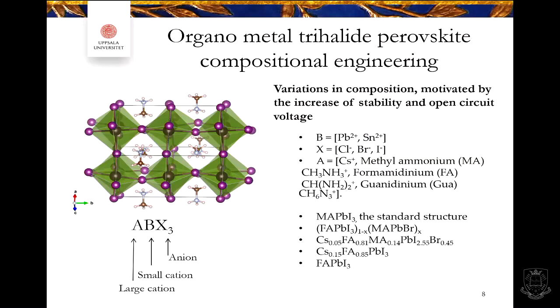So one other property which is unusual for semiconductors is that you can vary the band gap so much as you can in the perovskite structure. So you can exchange ions, the X here, to, for instance, bromide, and then you make the band gap broader. You absorb wavelengths that are shorter. Or you can change the A to other ions like cesium to stabilize the structure. FA is also stabilizing the structure more.